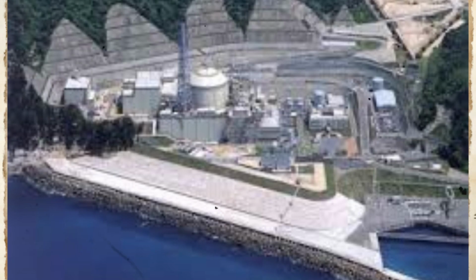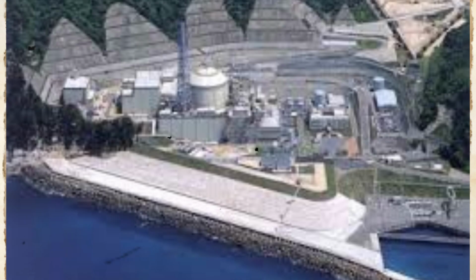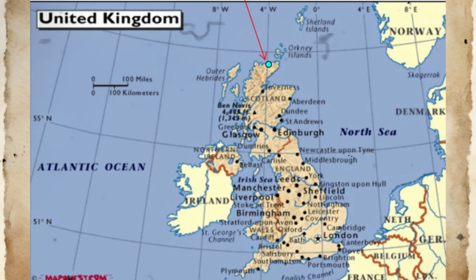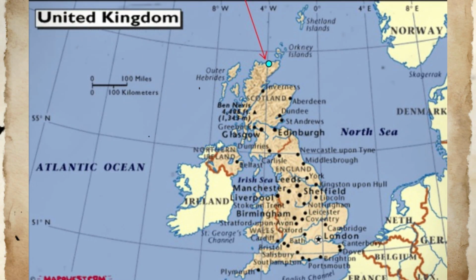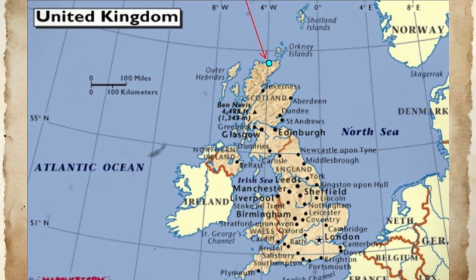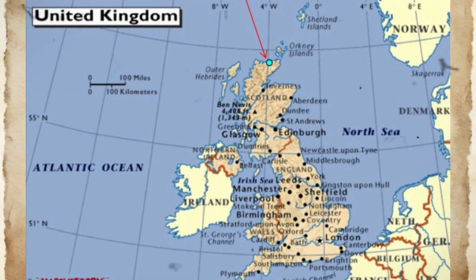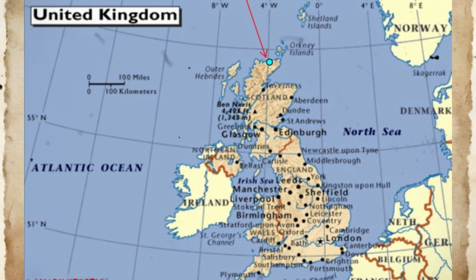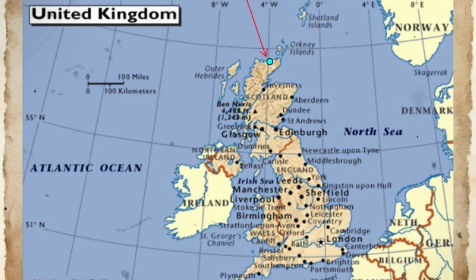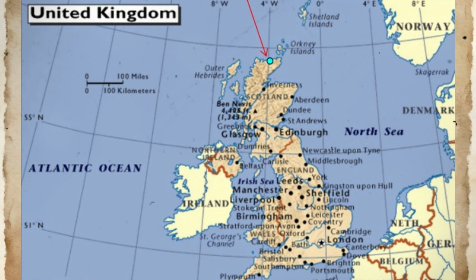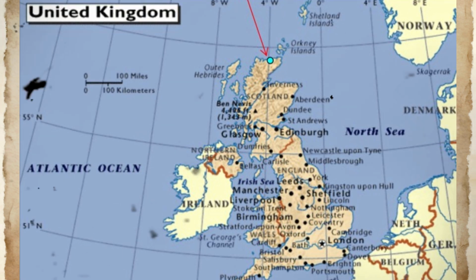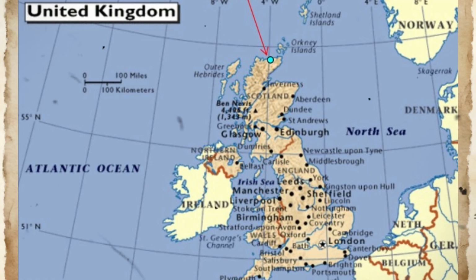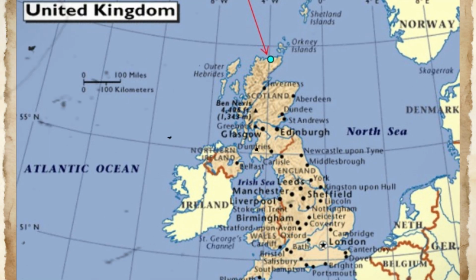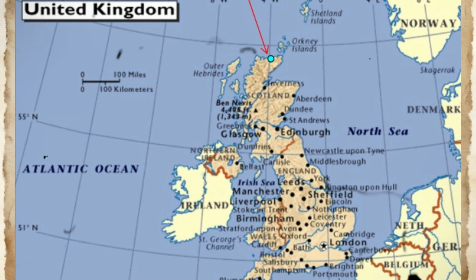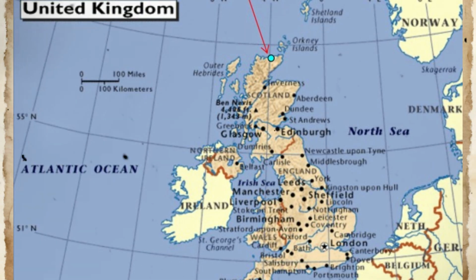The leak flow rate was insufficient to cause detectable pressure drop in the large volume secondary loop. System pressure was maintained by the secondary sodium pumps, which continued operating normally and compensated for the small inventory loss through normal pressure control mechanisms. The sodium inventory in each secondary loop was approximately 760 tons, providing substantial margin for small leaks without affecting system operation. Leak rates on the order of kilograms per hour would not significantly impact system inventory or pressure control. Only leaks involving substantial fractions of total system inventory would create detectable pressure or flow rate variations.